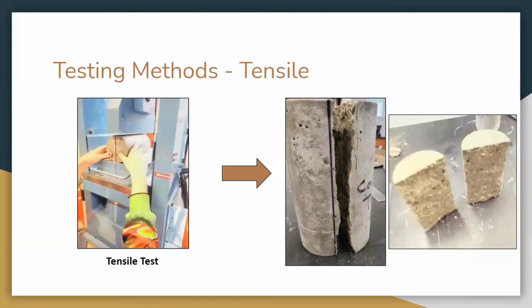Yeah. Next, we performed a split tensile test on each sample, where we drew a line across the diameter and length of the cylinders and laid them sideways in the machine shown in the picture on the left. Similar to the compressive test, this machine applied downward force on the sample until it split and recorded the weight the entire time. As you can see in the pictures on the right, the samples were split in half during this test, revealing the components inside of each sample.